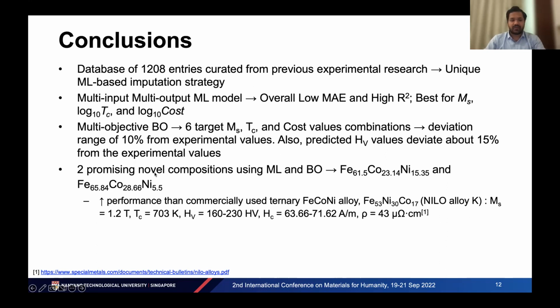Finally, we found two promising novel compositions, which are shown here, and this has a very high performance compared to the commercially used ternary iron cobalt nickel alloy.